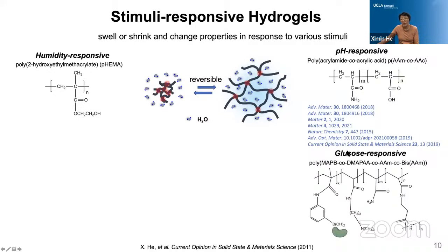And then, yeah, so based on this, you can also chemically design or functionalize your hydrogel network with some functional group. And for example, the boronic acid is known to be able to interact with the glucose molecule, so that this hydrogel becomes glucose responsive. It will change the volume or property in presence of the introduction of glucose molecule.